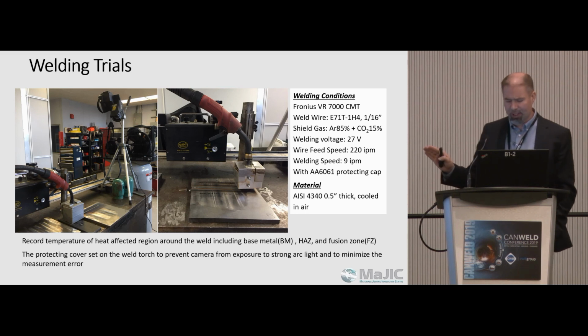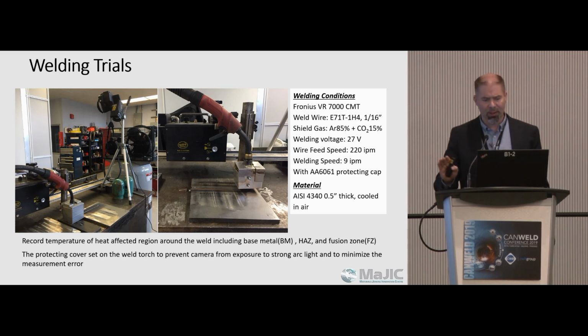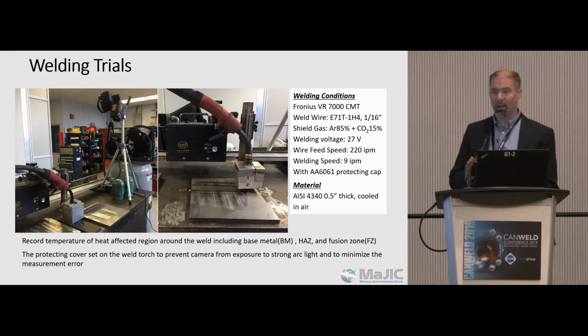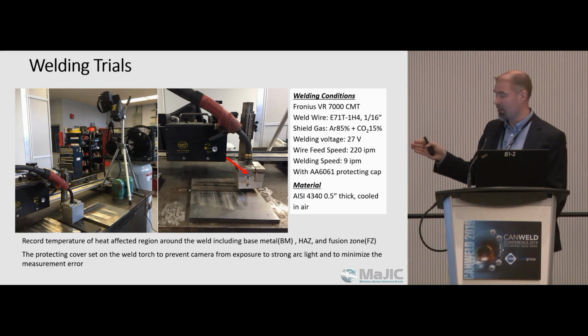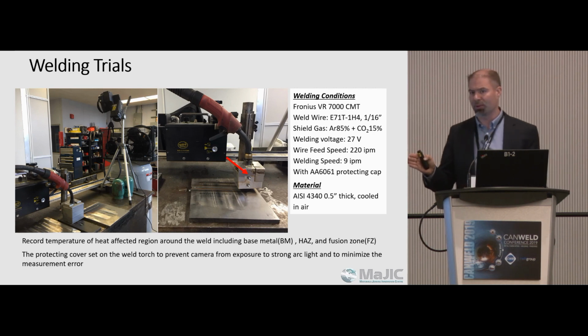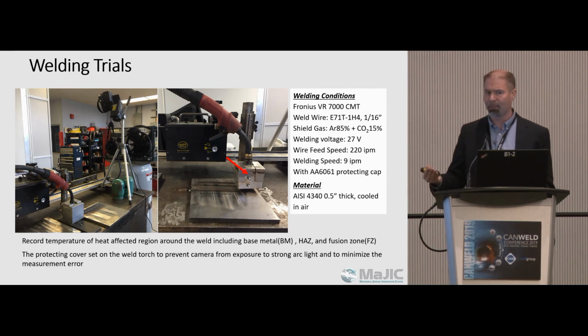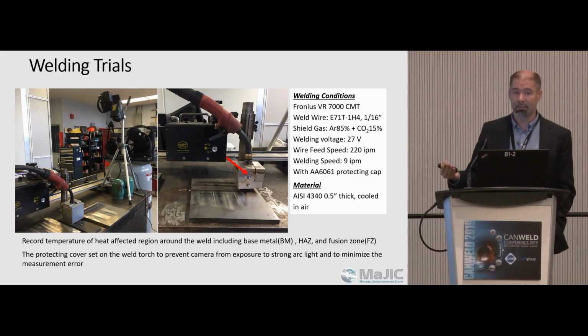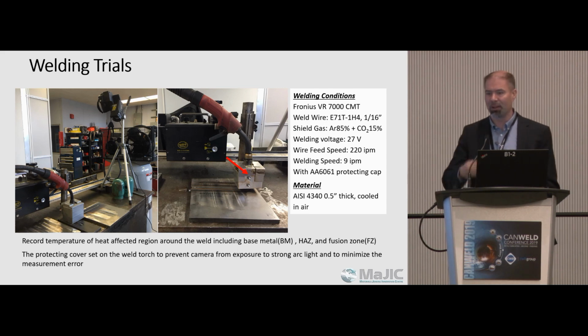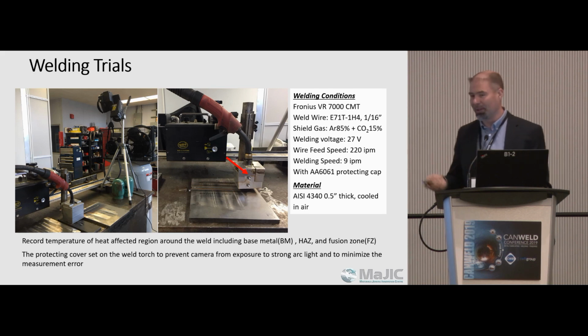So this particular sample that we're looking at was 4340, half-inch thick, and it was cooled in air. It is sitting on a steel table, so there's a big thermal sink there, and it was not preheated. That comes into play a little bit later. So we're looking at measuring the thermal cycle. We're not looking at making a good weld here, and you'll see in a minute what happens when you weld 4340 without preheat.